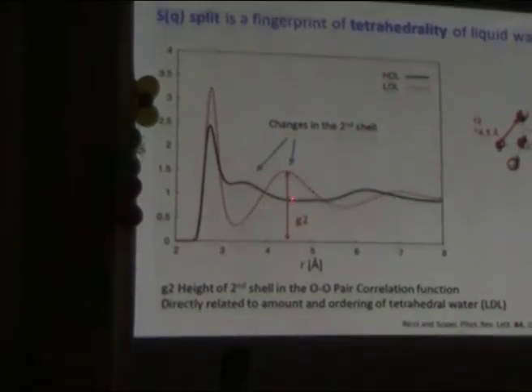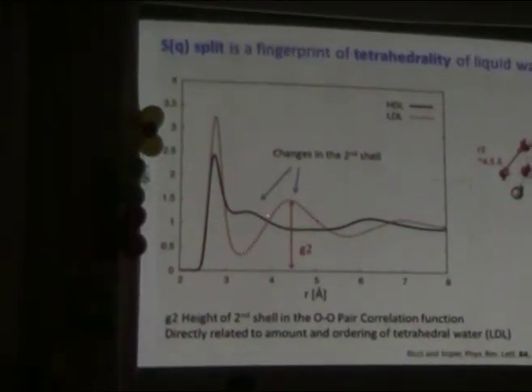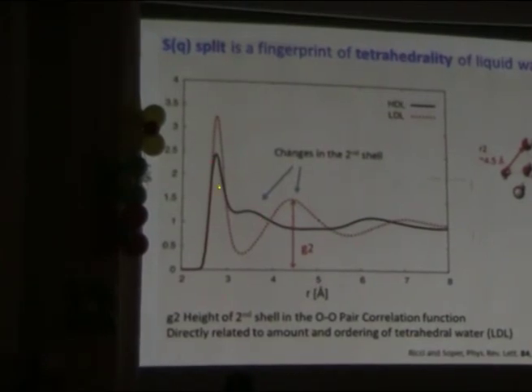The high-density liquid is characterized by a collapse of the second shell, and molecules also from the first shell have moved into the interstitial region. There's very little contribution here. Now this position corresponds to the distance between the nearest neighbors to this molecule.